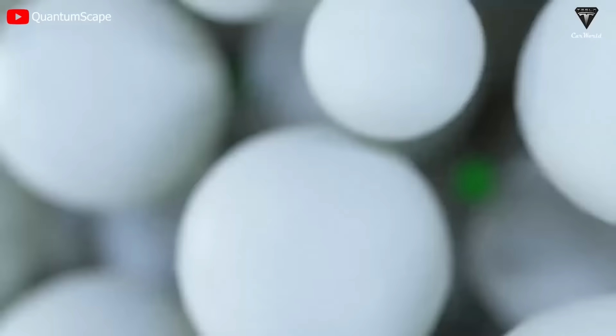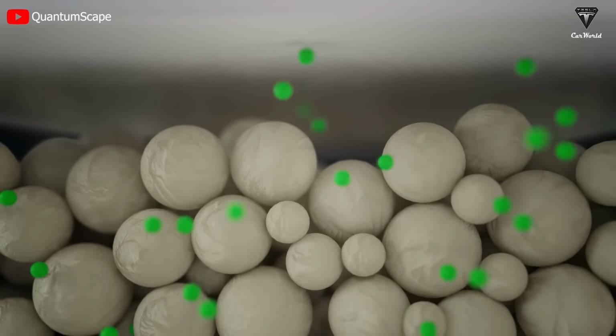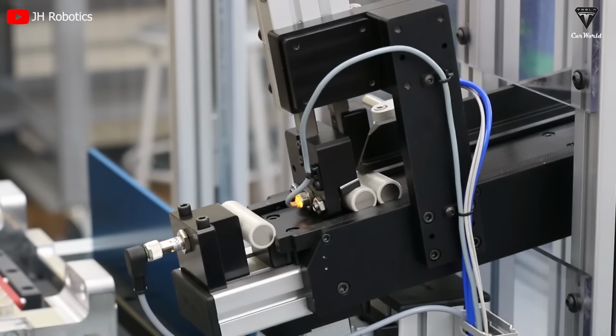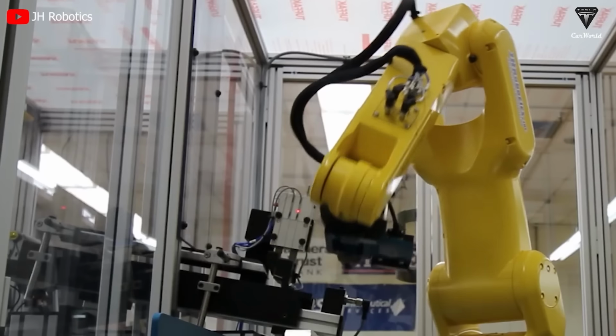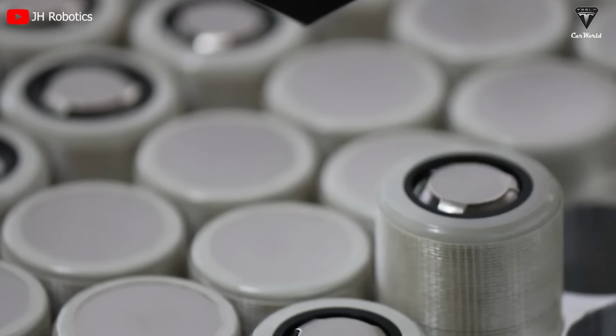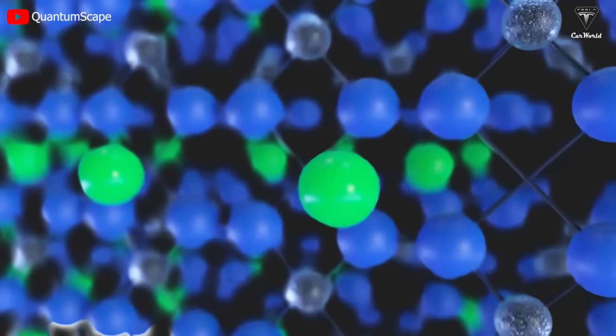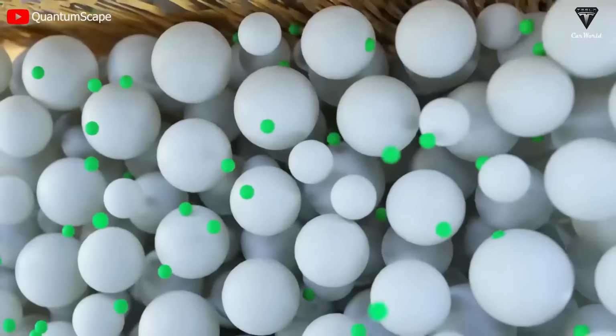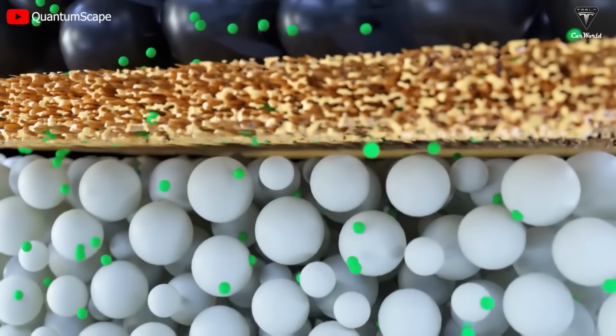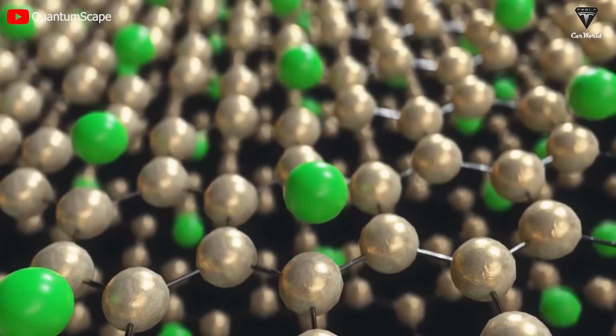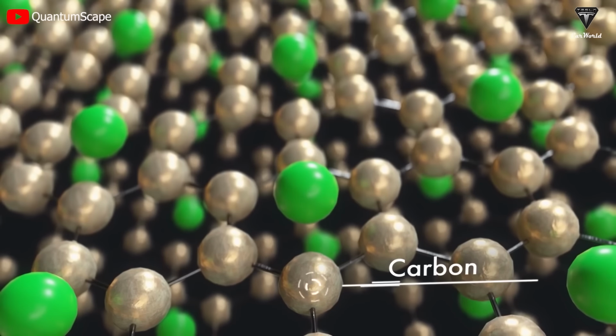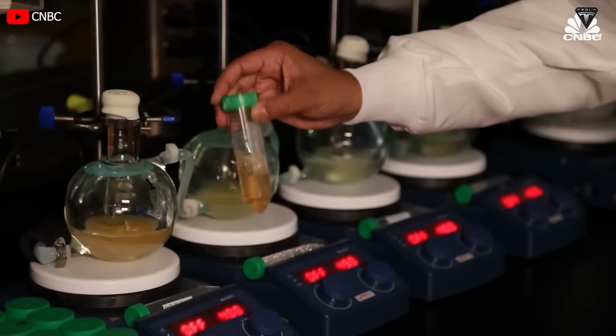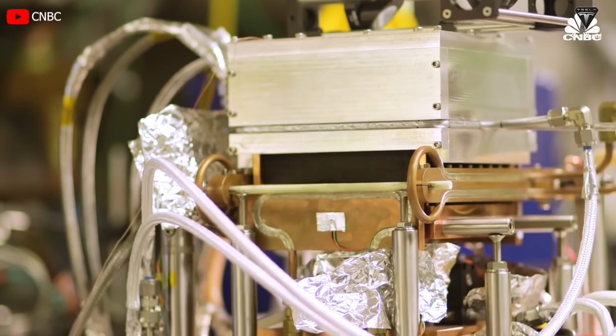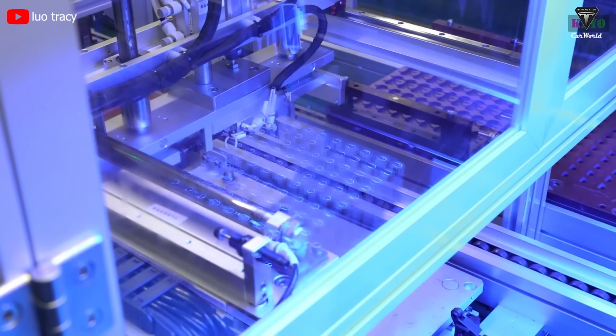This change results in a high-capacity nanostructure, 1.6 times higher, or 60% higher, than the previous generation's technology primarily made of graphite. In sodium-ion batteries, a higher-temperature-synthesized hard carbon called G1500 outperforms lower-temperature hard carbon at a lower current density. The superior performance of G1500 is attributed to the balance between defects, as well as interlayer spacing and porosity, making it better equipped to store sodium ions compared to a hard carbon battery synthesized at lower temperatures, known as G1000.